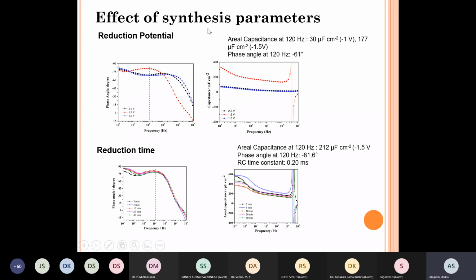Then we looked at the effect of synthesis parameters. So reduction potential, different reduction potentials of -1 and -1.5 volts. And as you can see, at -1 volt, there is certain performance, -1.5 volt is much better, and when we go to minus 2 volts reduction, then it again deteriorated. So we selected -1.5 volts. Capacitance is also shown. The left-hand side is the phase angle to show it is still capacitive, and the right-hand side curve shows the areal capacitance.